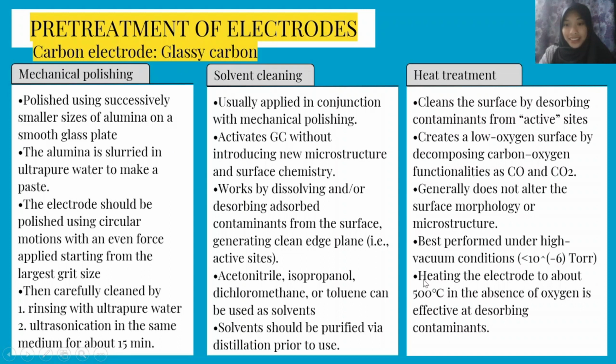pressure. And this heat treatment is carried out by heating the electrode to about 500 degrees Celsius in the absence of oxygen, and it is effective to desorb contaminants.